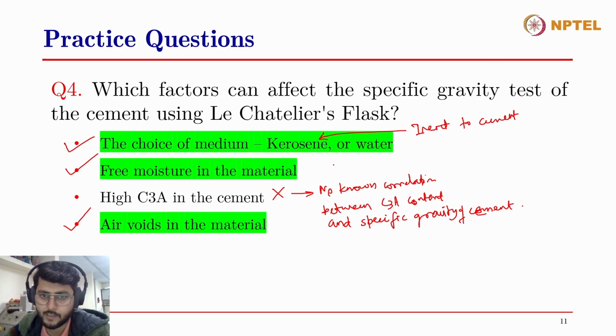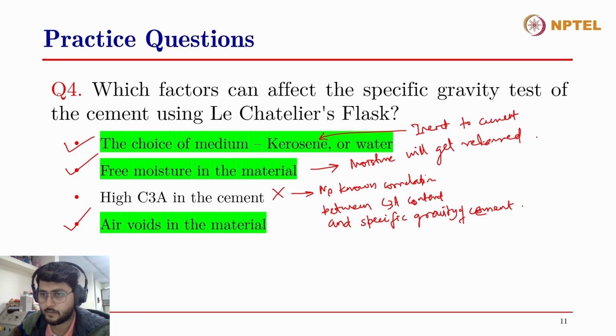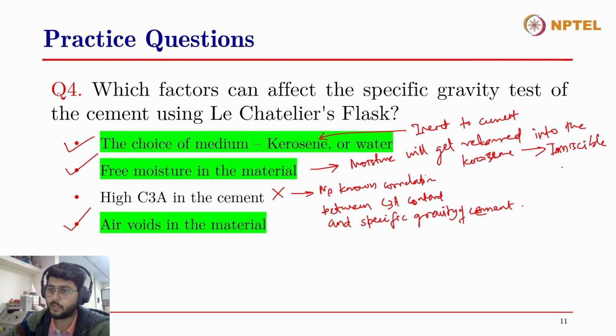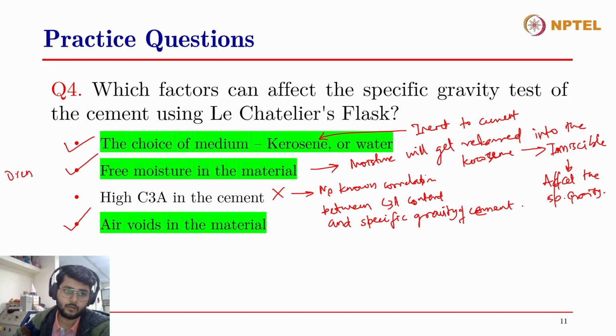Then the free moisture in the material, as discussed in the fineness measurements as well. If there is free moisture in the material, then this moisture will get released into the kerosene, and since kerosene and water are not miscible, therefore it will affect the specific gravity. So you need to oven dry the material prior to carrying out your specific gravity test.